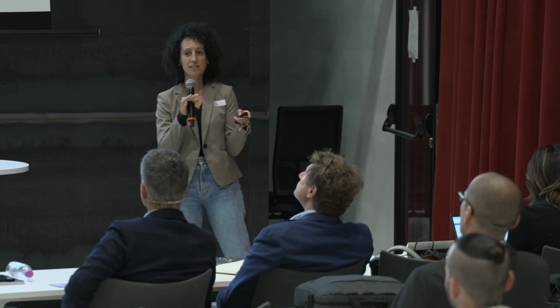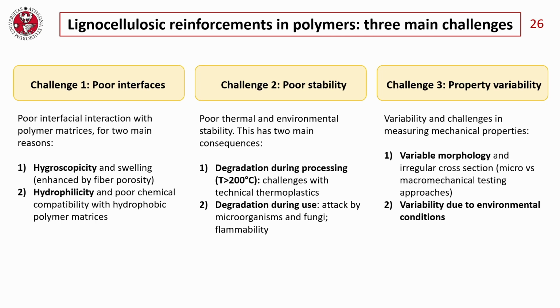The third challenge is instead associated with the property variability. In fact, they are both variable in time and from batch to batch. And it is also challenging to measure their properties because their cross-section, for example, is not constant. They are not perfectly cylindrical, for example. Their properties vary depending, for example, on the different locations on which they are grown, on the different precipitations, the different temperatures on which they are grown. And these are not only controllable variables.